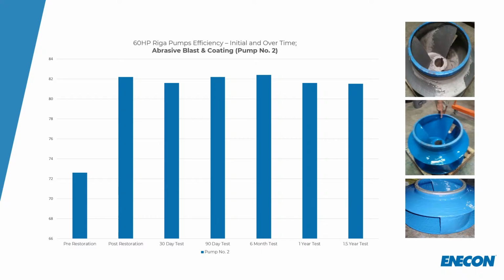So pre-restoration, you're sitting on this one at about 72.5%. The coating was performed. You can see you're up at 82%. 30 days, 90 days, 6 months here, 1 year, 1.5 year. You see it holds up pretty steady on this.